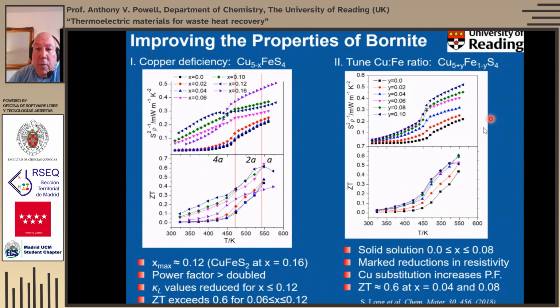We can get similar performance on a similar basis by just tuning that copper to iron ratio, which again results in oxidation of some of the copper. And once again, we can get to ZT of about 0.6.